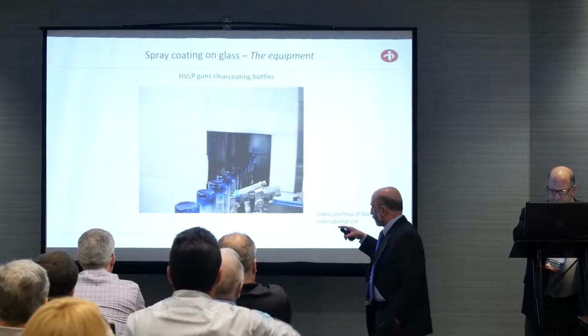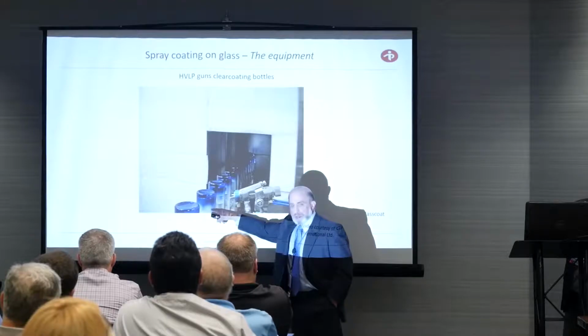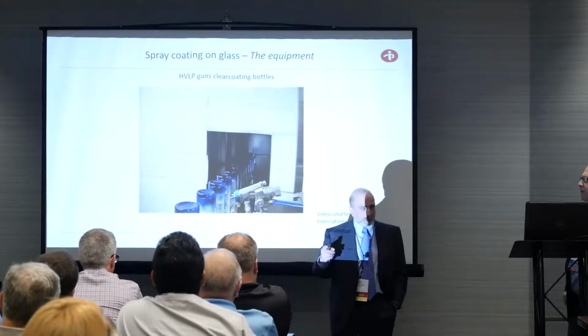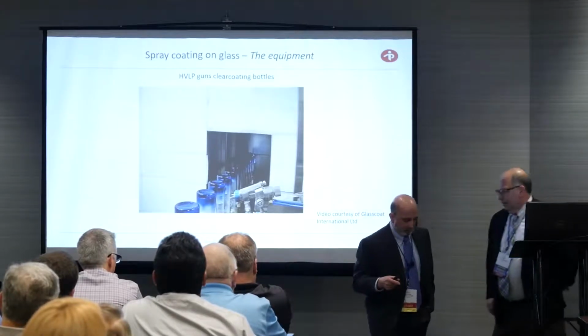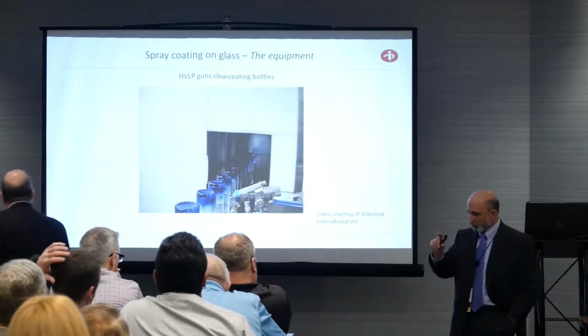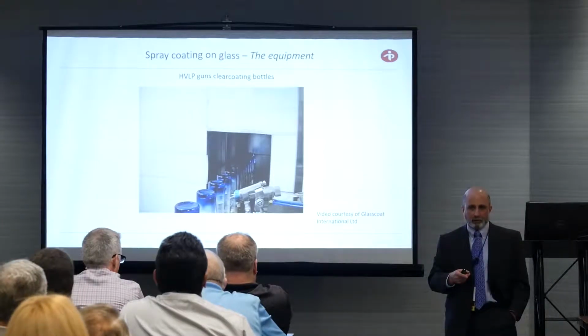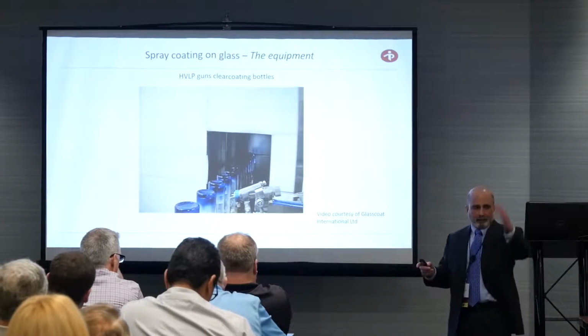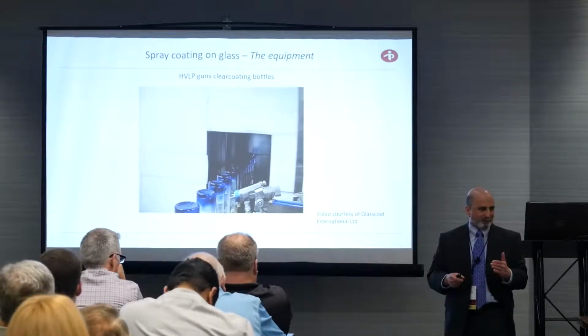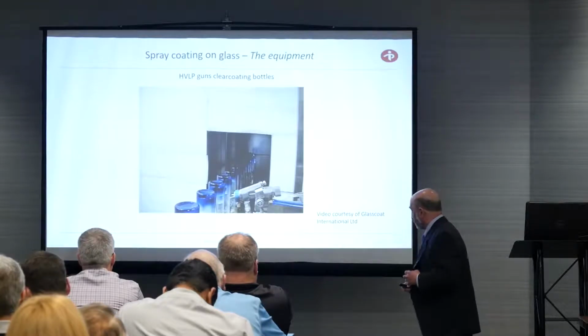That means you're putting a very low film weight at this point of the bottom, right? The lower the film weight of the coating, it's true whether you're talking about screen printing or anything, the more you reduce resistance properties. So to protect it, we always recommend a clear coat over the top. That's what's happening in this process.